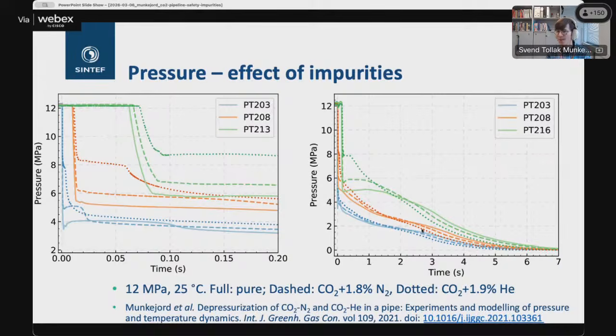Then there is an interesting point that I'd like to talk about briefly here on the plot where I show a longer time series. So initially, the full line here for the green one is at a lower pressure, as you can see also to the left, but after 2.5 seconds, more or less, the curve showing the pure CO2 has the highest pressure. So there is an inversion. And the reason for this, in our understanding, is because pure CO2 has a lower pressure propagation speed for a fully dispersed gas liquid mixture, which you have at the outlet. So this means that the pipe with pure CO2 is emptied slower than the ones with mixture.